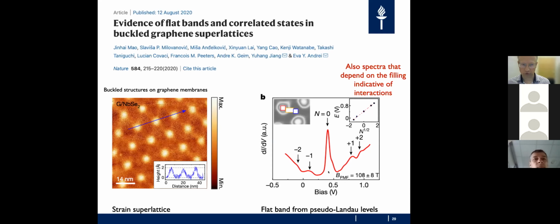But in addition, they show in their studies that the spectra depend on the filling, and this is indicative of strong interaction effects. But they haven't really reported what type of interaction effects would be present. It's very difficult to make transport studies in these systems.